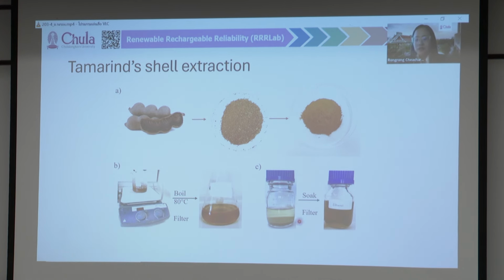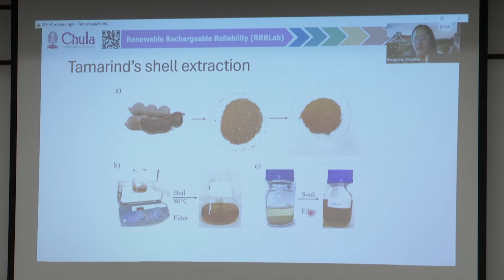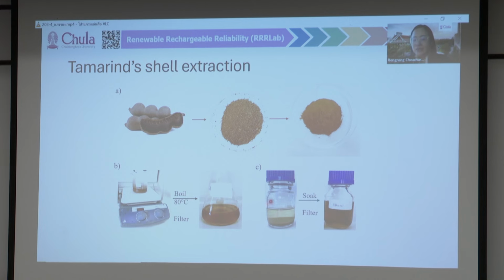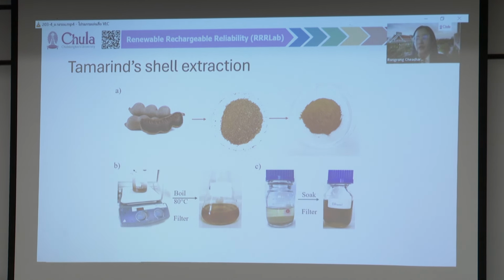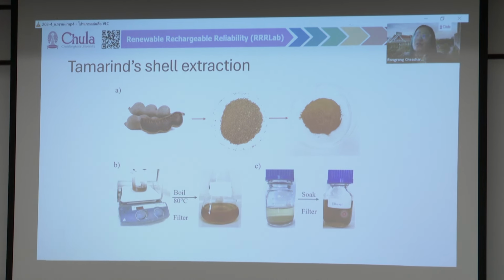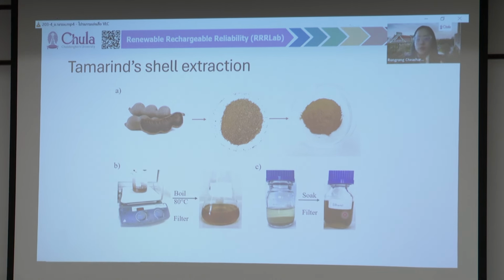However, we also explored another way where we can extract the chemicals from tamarind in advance. In this case, we put the tamarind powder in an ethanol solution and let it soak there for a day, and then we keep collecting this ethanol solution, and at the end we take it to the rotary evaporator to get a more concentrated tamarind extract. Of course, after we get this, we can keep it in the fridge and use it whenever we want to do the battery material synthesis. But the problem is we didn't find a source of potassium in this case. So there's a trade-off between the two methods.